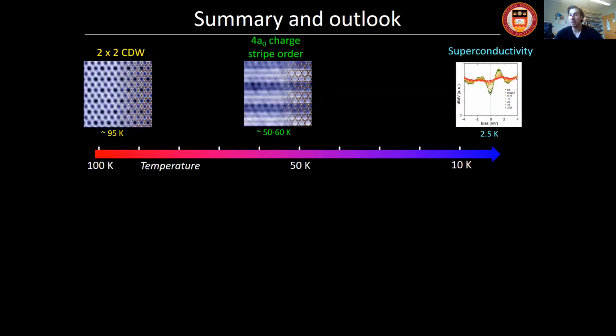Okay, so this brings me to the summary and outlook of what I told you about today. In these vanadium-based Kagome superconductors, we found this surprising 4a0 charge stripe order that onsets at about 50 to 60 Kelvin. That's an intermediate temperature between the onset of the 2x2 bulk charge density wave state at 90 Kelvin and superconductivity at about 2 Kelvin.